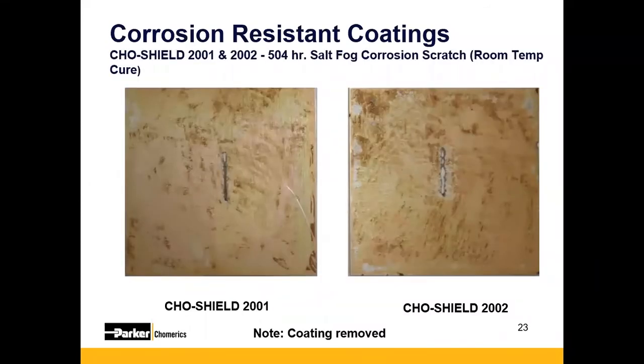And this is a picture. We talked about soluble chromates. It's a very good corrosion resistant technology, however, with environmental laws. So with our 2000 series, this is an aluminum plate. We painted it with 2000, scratched the plate, and put it through the 504-hour salt fog test. As you can see on the right-hand side, the Cho-Shield prevented the corrosion from spreading where the scratch was. And even with the 2000 without the soluble chromates, it still maintained excellent corrosion resistance. It's just slightly less good of performance, but still a good choice.